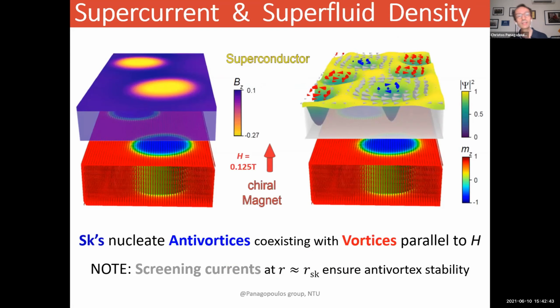So what you find is that skyrmions, shown here in blue color, nucleate anti-vortices, shown also in blue, in the superconductor. Now, the superconductor is on top, and your magnet, your multilayer, is on the bottom. So this magnetic blue skyrmion nucleates anti-vortices inside your superconductor on the top. And these anti-vortices coexist with superconducting vortices in the superconductor, shown here in red, parallel to the magnetic field.